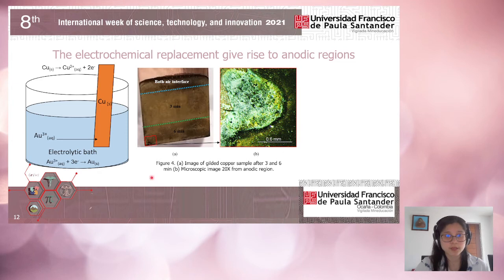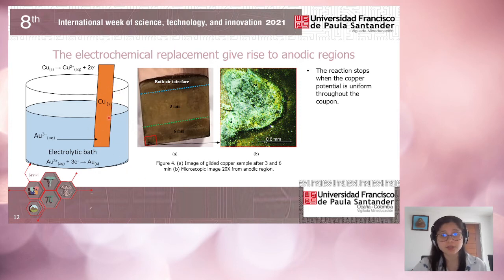In figure 4, we can see the result of our gilding. The reaction, as I already mentioned, stops when the copper is totally oxidized or when the potential is uniform throughout the coupon. Thus, anodic zones must be totally covered. As you can see from figure 4, there were still anodic regions seen in the 6-minute region. Below the green dotted line, we can see the 6-minute region, and in different corners, you can see these anodic regions. In general, between the 3 and the 6 minutes, you can see uniform plating throughout the immersed piece.